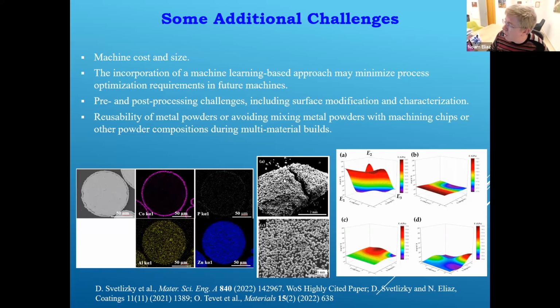And you see at the top part, when we don't use this process and we put this powder in the furnace, you have this kind of agglomeration, a spongy, brittle piece that is formed. When we use this surface modification in-house, the same powder, the same furnace, the same treatment, you don't see this kind of agglomeration.